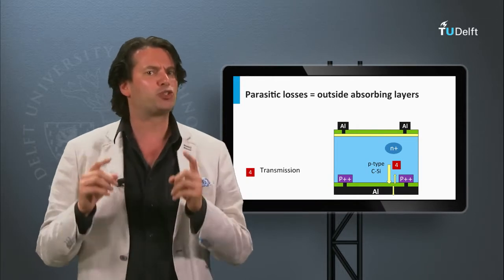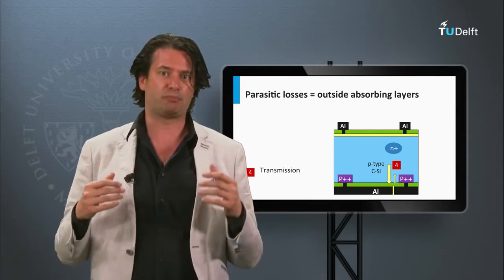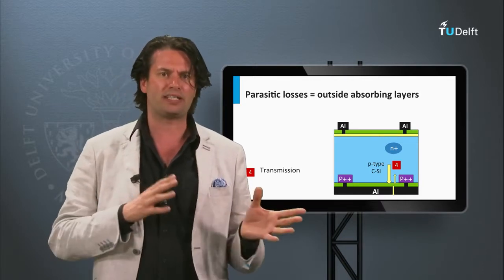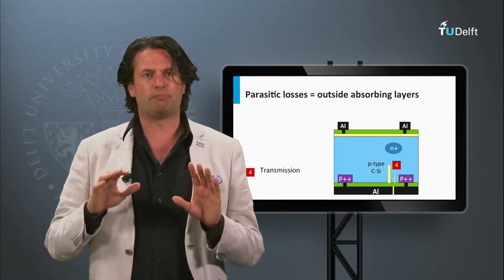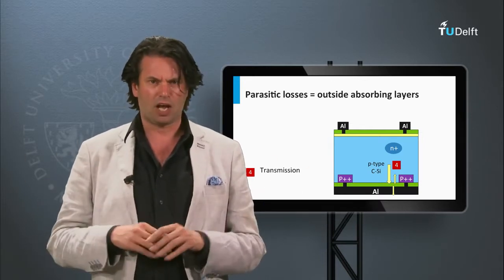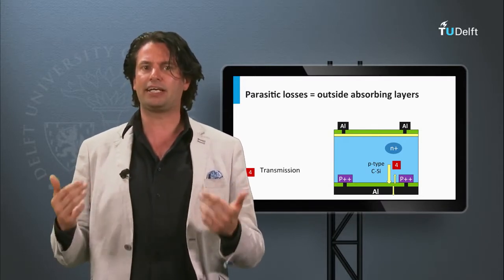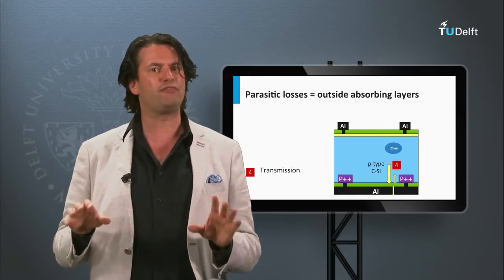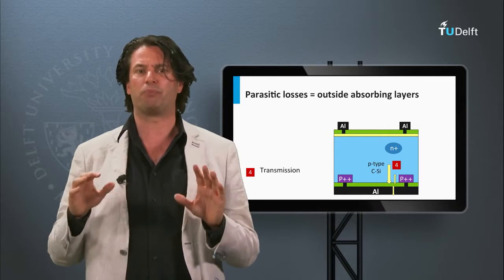Secondly, if the absorber layer is not thick enough to absorb all the light, part of the light will be transmitted. As the absorption coefficients are larger in the blue spectral part, this usually plays a role in the red to infrared part of the solar spectrum. The light transmitted can be reflected back, which is a so-called back reflector. Some of the light can also be absorbed at the back contact. This can again be considered as a parasitic absorption loss. In week 5, we will discuss thin film solar cells, where back reflectors and light scattering on the angles start to play an important role.